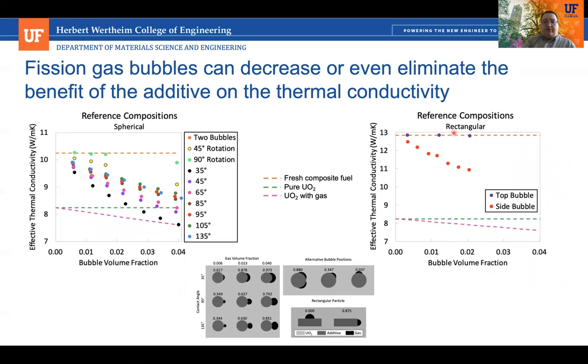And then here we have the rectangular particles with the same lines. The first thing that we see is that depending on the particle or on the bubble position and wetting angle and volume fraction, we get a very large scatter. When we have the bubbles rotated so they're up on the top of the particle and they're not blocking any of the heat transport through the particle, they have almost no effect in both the sphere and the rectangular particles.